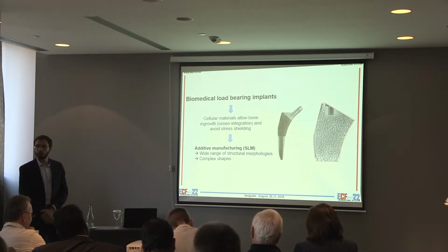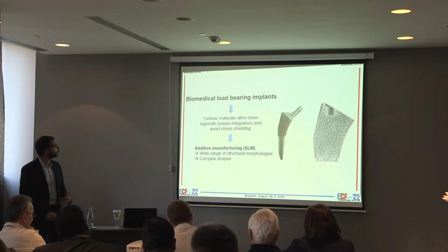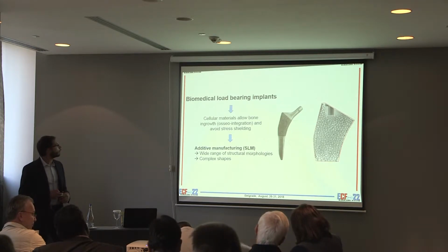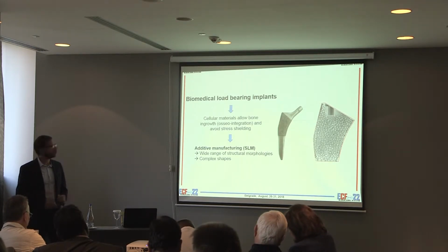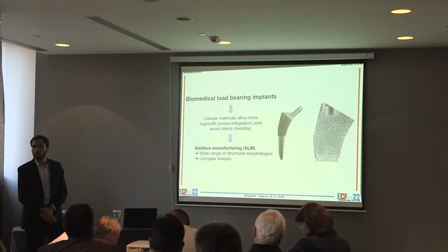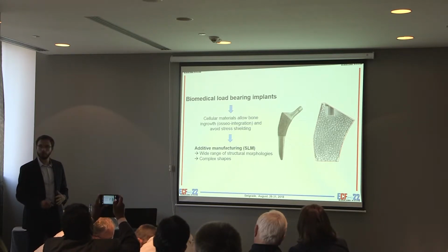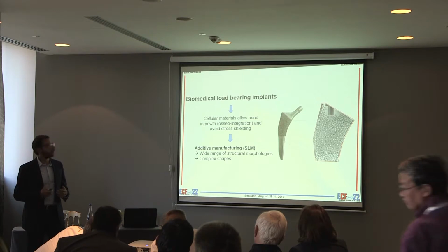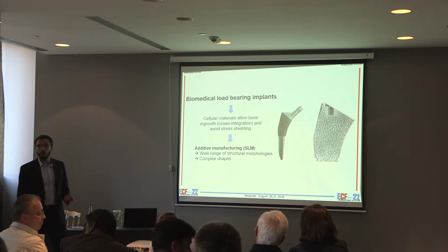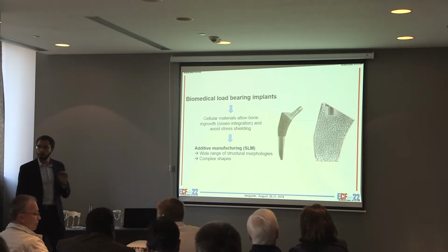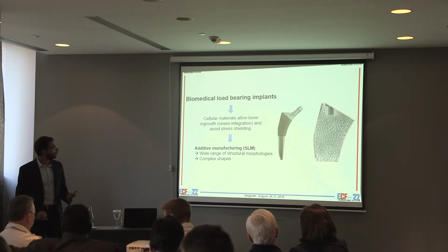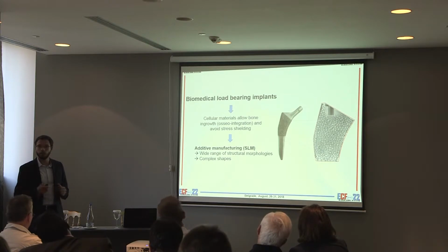This has already been introduced by a previous presentation, but the advantage of these materials in the biomedical field is due to the fact that they are porous, so they allow bone integration, and they also avoid the stress shielding phenomenon, which is basically due to the difference in stiffness between an implant and the bone. If we use a fully dense implant, which is much stiffer than the bone, we basically underload the bone nearby the implant, which then resorbs, and thus the interface between the implant and